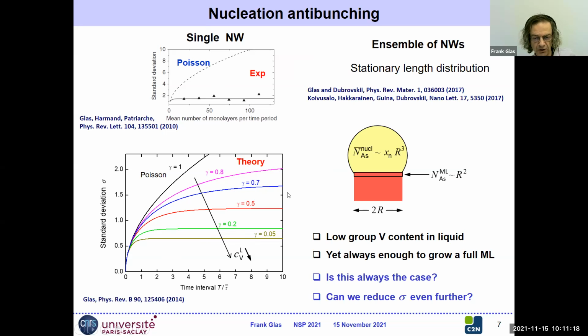Obviously, this phenomenon of nucleation anti-bunching is related to the low group 5 content in the liquid. However, in this first approach of 10 years ago, we assumed that there were always enough arsenic atoms at nucleation in the droplet to grow very fast a single monolayer. And the question arose, is this always the case?